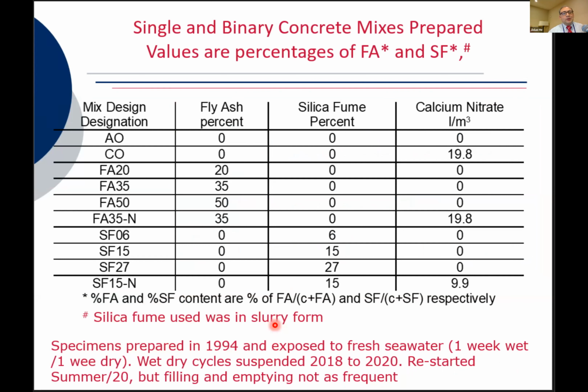I'm not going to take too long to describe the different compositions, just to let you know that there were 4 different mixes that contain fly ash ranging from 20% to 50%. And there were a couple of them that had only Portland cement, but one had also an inhibitor added to it. And then there were 4 compositions that contain silica fume. In this case, these samples were prepared in 1994, and the silica fume is in a slurry form, not in a powdery form. So there was some water that was counted toward the water to cementitious ratio. All of these samples were prepared with a 0.37 water to cementitious ratio.